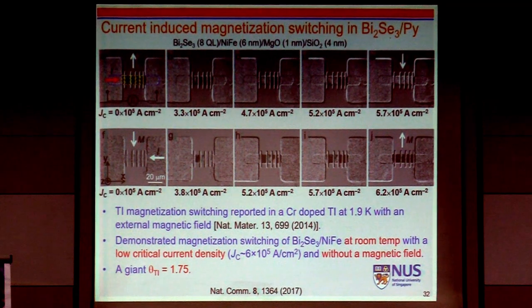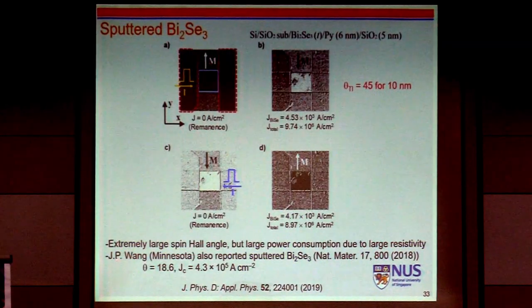But still, the problem is the bismuth selenide is grown by molecular beam epitaxy, which is not really scalable technology. Then we noticed a very interesting report by Jinping Wang group in Minnesota. They showed sputtered bismuth selenide can give rise to a very large spin Hall angle, like 18, and the switching current density was 4 times 10 to the 5 ampere per square centimeter. So motivated by this work, I followed a similar approach.